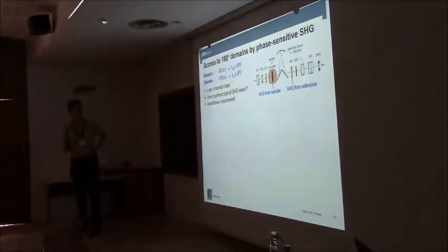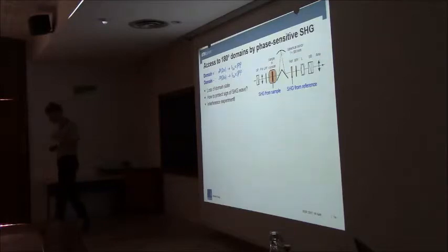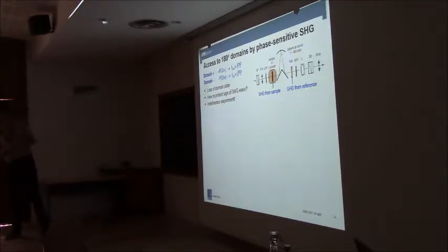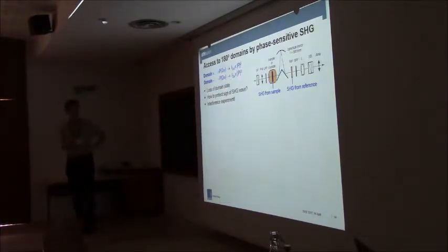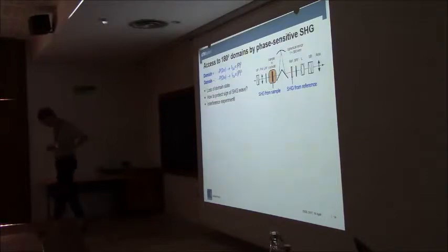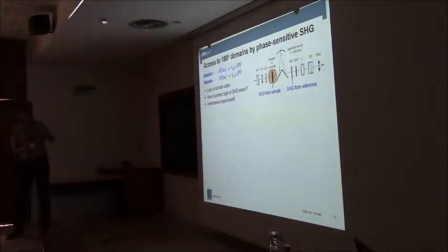So these two domain states would give you a second harmonic light field plus P of 2 omega, and the other domain would give it to you with a sign, minus P of 2 omega. A minus sign in a polarization wave is a 180-degree phase shift. Exponential i pi is minus 1. But then when you measure intensities, it's all the same. So you cannot distinguish two domain states, but you want to distinguish them. You want to see the domains.